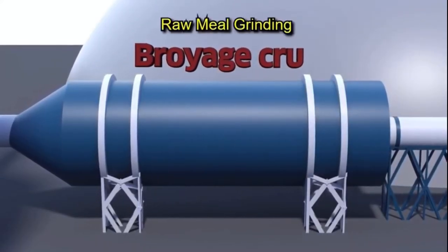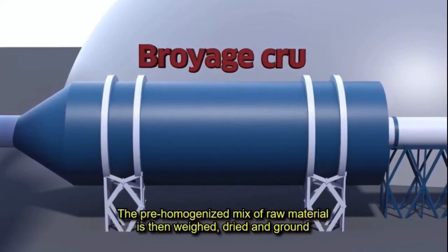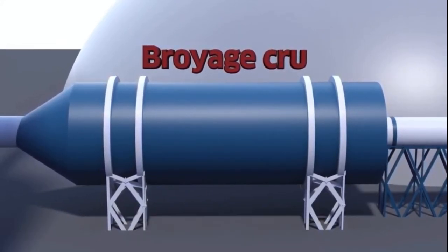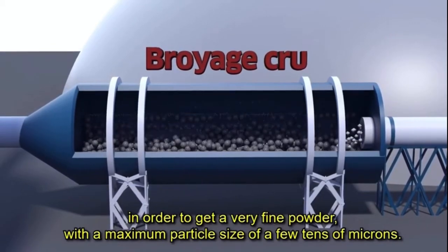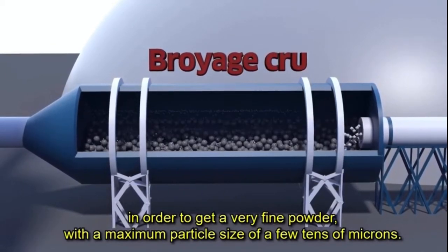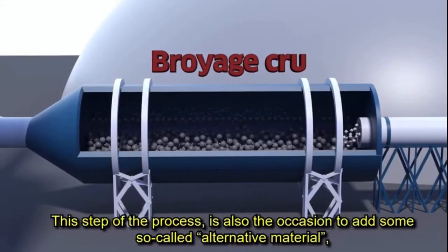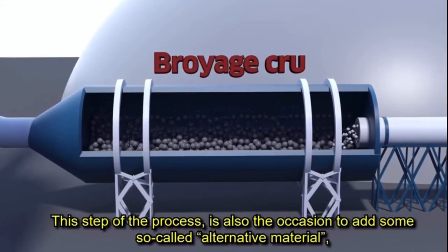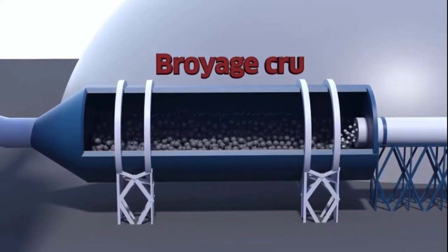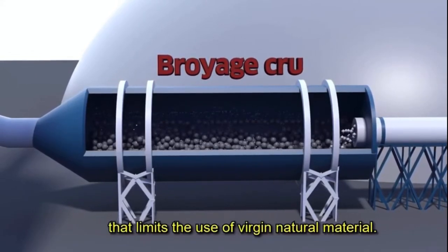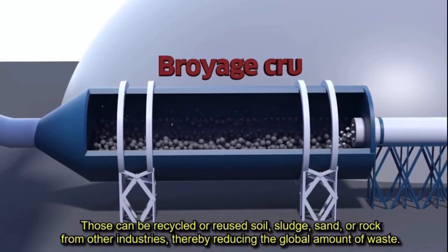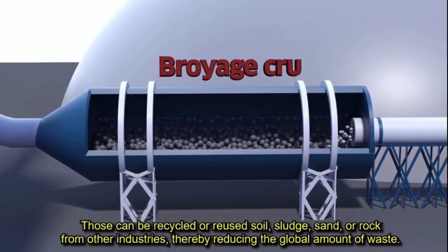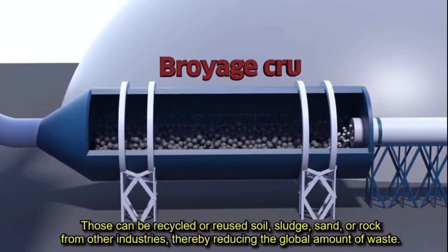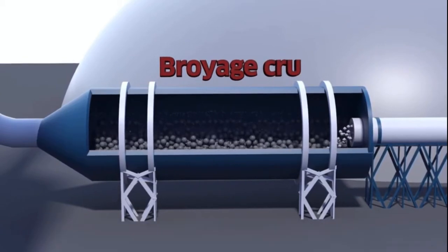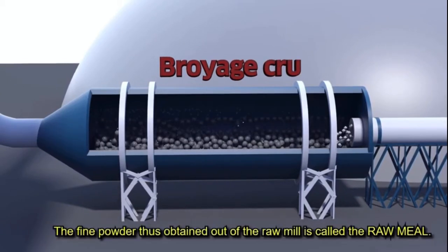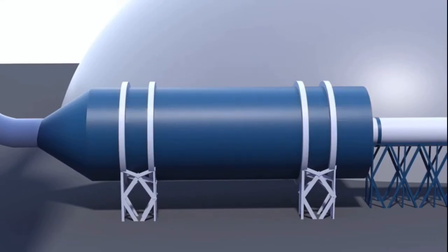Raw meal grinding. The pre-homogenized mix of raw material is then weighed, dried and ground in order to get a very fine powder with a maximum particle size of a few tens of microns. This step of the process is also the occasion to add some so-called alternative material that limits the use of virgin natural material. Those can be recycled or reused soil, sludge, sands or rocks from other industries, thereby reducing the global amount of waste. The fine powder thus obtained is called the raw meal.